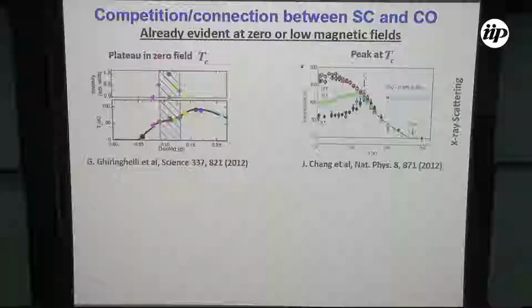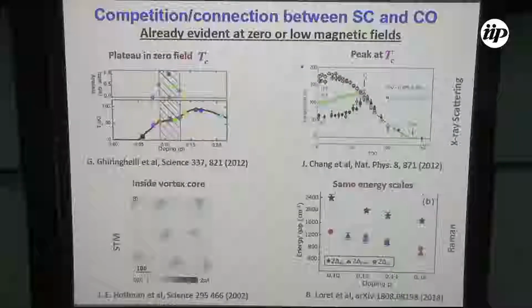This competition is also evident if we look at STM measurements. If we put some small amount of magnetic field, there would be vortices in the sample, and inside the vortex core, the superconducting order parameter would be depleted. Once the superconducting order parameter is depleted, you can see that there would be charge order or charge modulation seen inside the vortex core. And very recently, it was seen in Raman measurements of Professor Alain Sacuto's group.